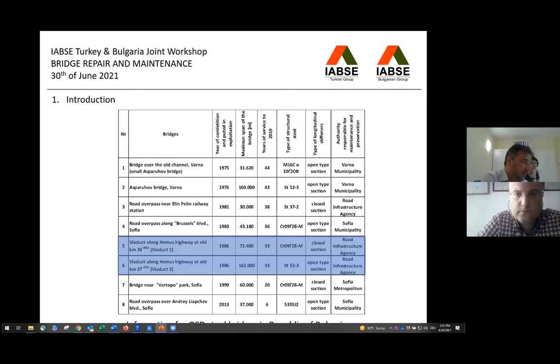Actually, the wide construction of the orthotropic deck started in the 60s, 70s of the last century, and the bridges that are in exploitation for 30, 40 years or more have shown one main problem with the orthotropic steel decks, which is fatigue damage accumulation. They have a number of complex details and crossings between elements that can lead to low fatigue strength zones. In accordance with some literature and the practice in the Netherlands especially, the fatigue cracks occur after 20, 30 years of service. And then you have to take adequate measures to restore the reliability of the bridge.